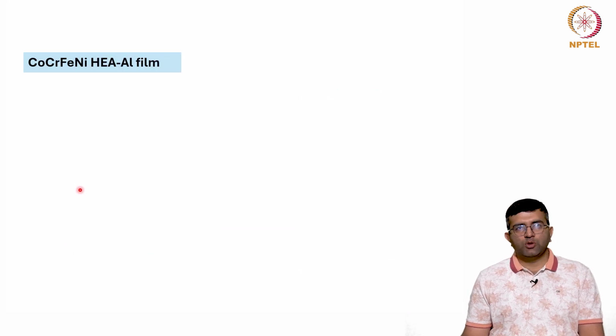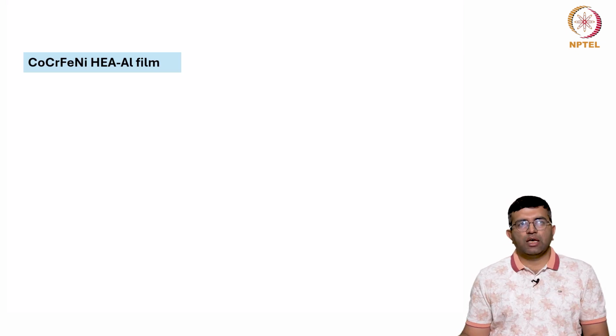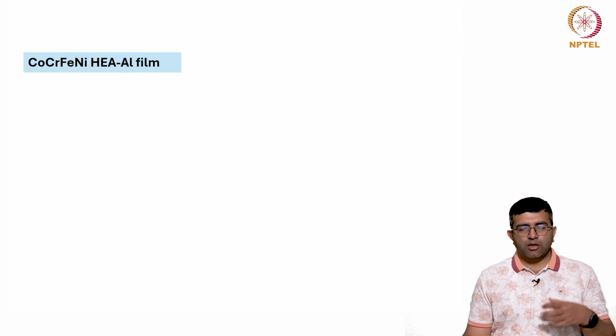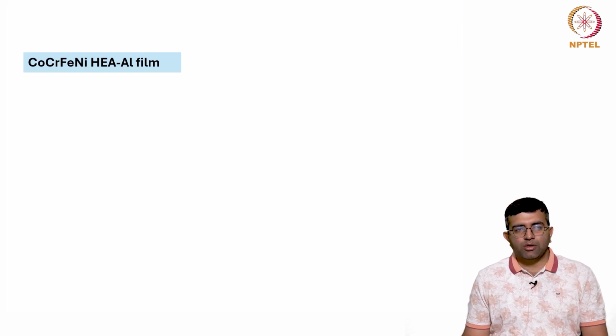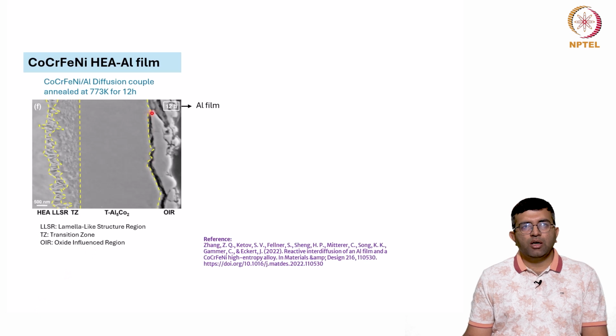Another way of doing a diffusion couple in a multi-component alloy is not to go for the pseudo binary, but to go straight away for, let us say here in this case, a cobalt, chromium, iron, nickel and aluminum diffusion couple. So, here it is not a pseudo binary case. The objective many times is to understand what phases will form in the interdiffusion zone. You see here an aluminum foil, and here there is a high entropy alloy. You can see already a complex interdiffusion zone developing.